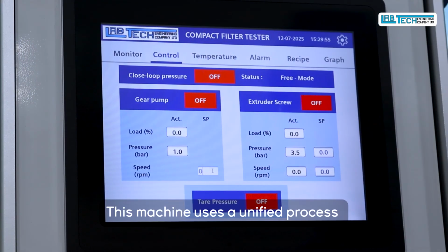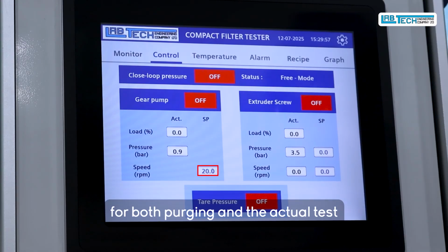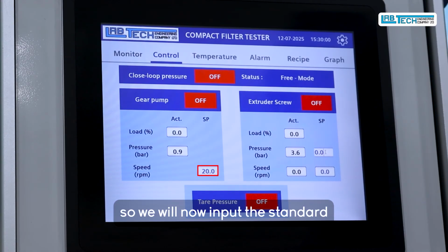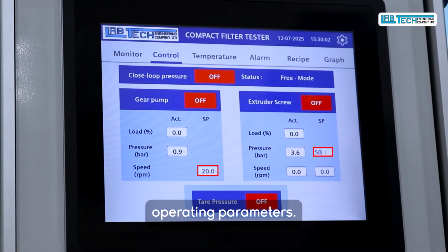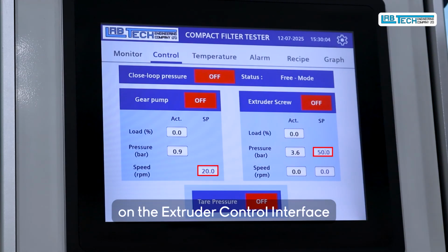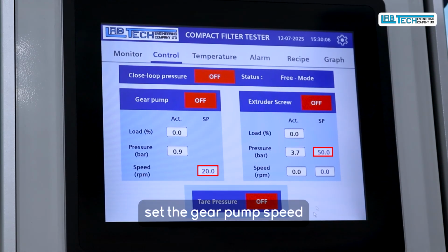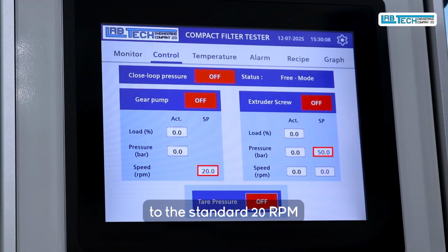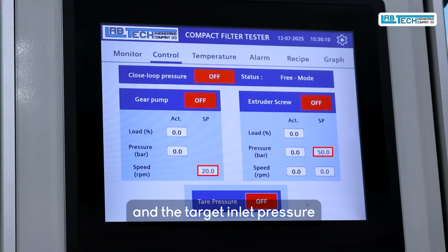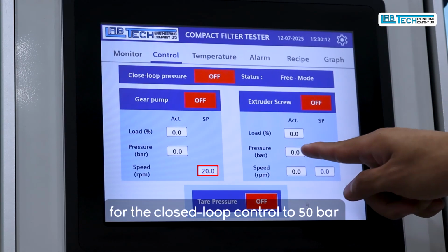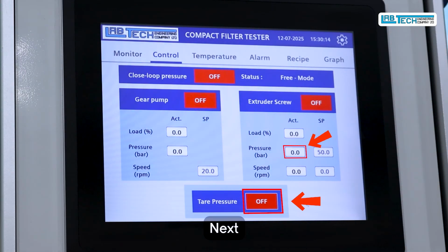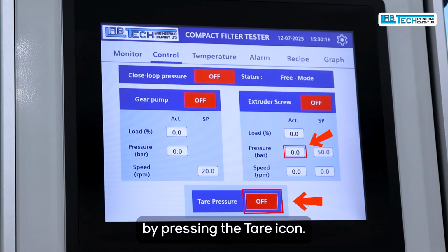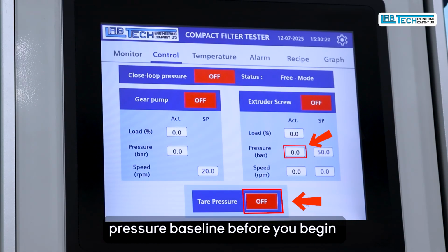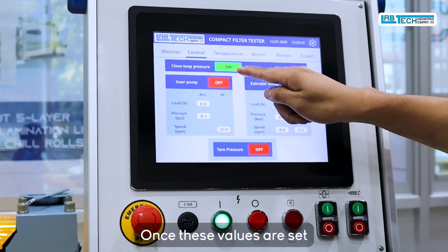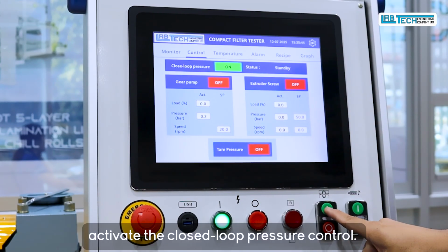This machine uses a unified process for both purging and the actual test, so we'll now input the standard operating parameters. First, on the extruder control interface, set the gear pump speed to the standard 20 RPM and the target inlet pressure for the closed loop control to 50 bar. Next, it is critical to tare the pressure by pressing the tare icon. This establishes a true zero pressure baseline before you begin. Once these values are set, activate the closed loop pressure control.